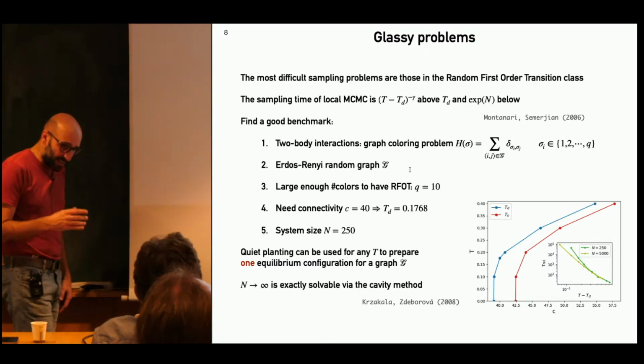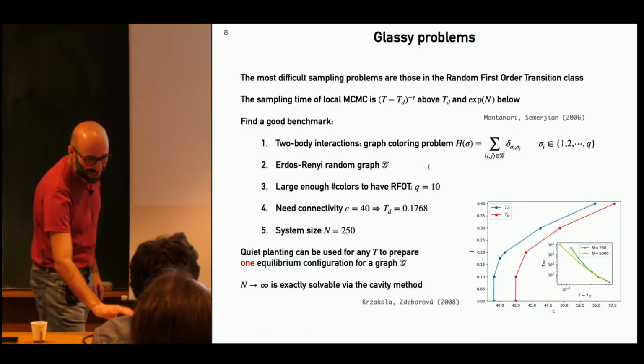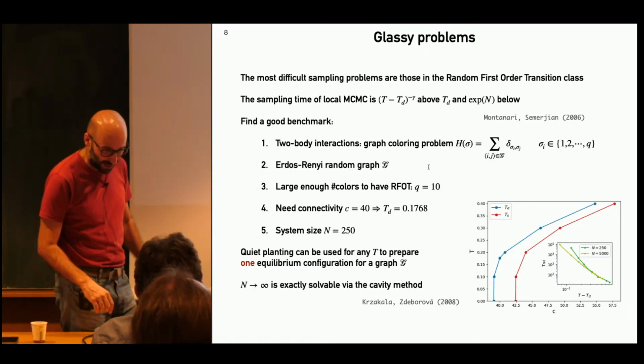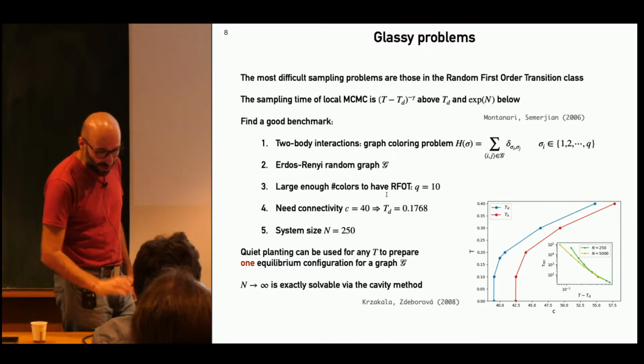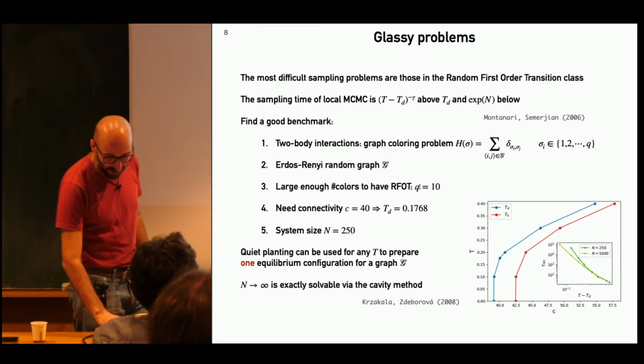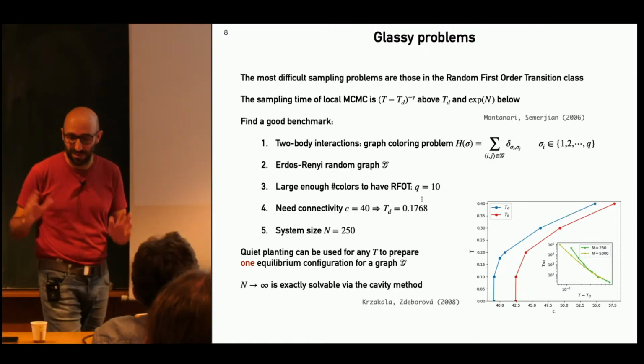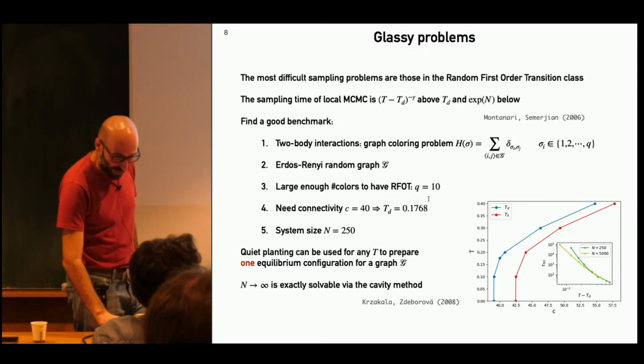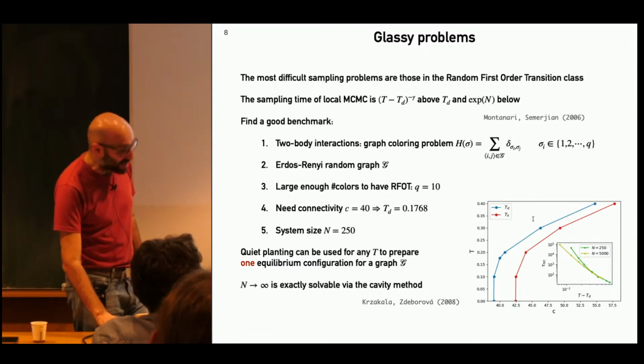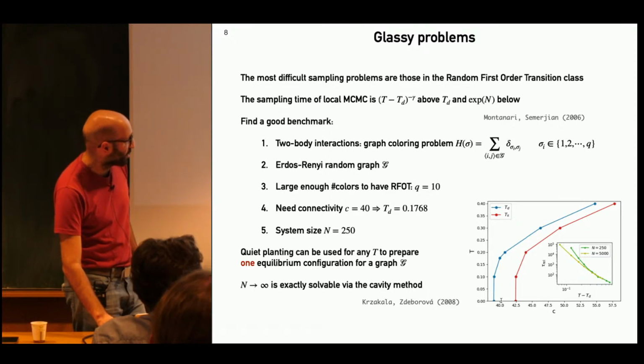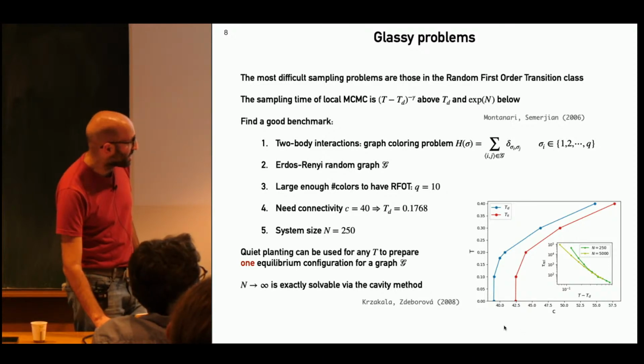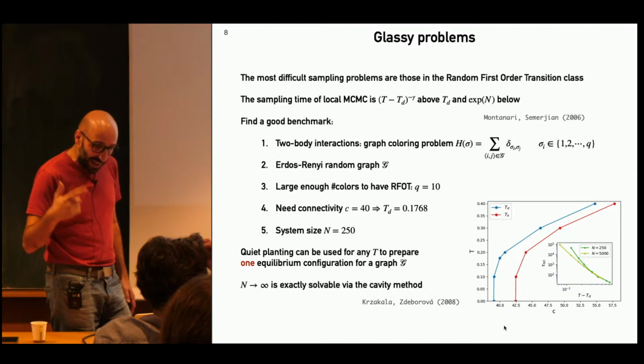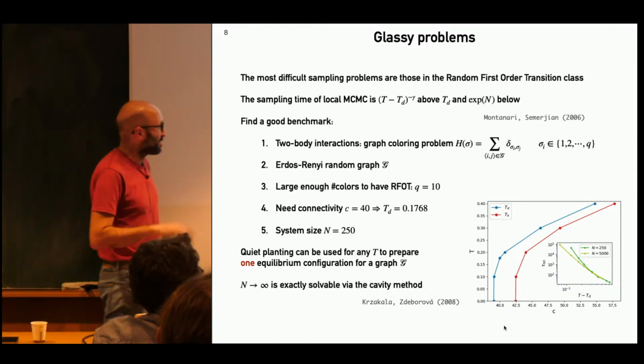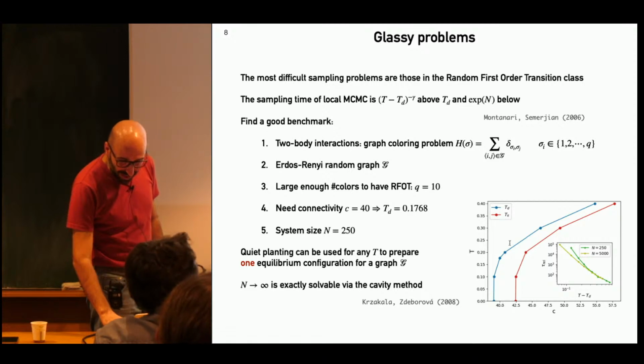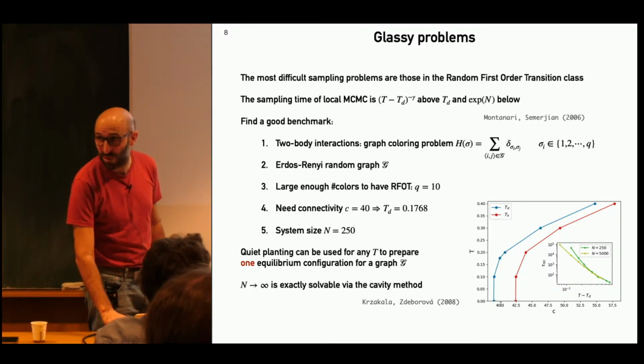This is a well-studied problem, and what we know is that it's not always in the RFOT class. Sometimes it's more like the spin glass. So in order to have a strong RFOT system, you need a large enough number of colors. We took 10, that was the minimal one, to have a good separation between the different transitions. Now if you look at the phase diagram for 10 colors, here you have the connectivity of the graph, and here you have temperature. You have two transitions. The blue line is the dynamical transition, where the sampling becomes hard, and the red line is the Kauzmann transition, where you go into an ideal glass. In order to get some hard sampling region, we need at least connectivity 40. So that's what we chose.